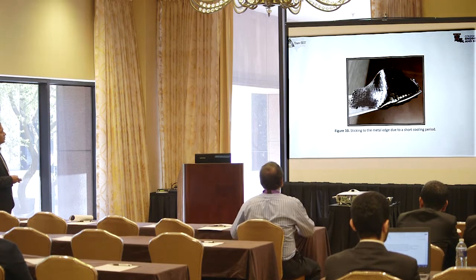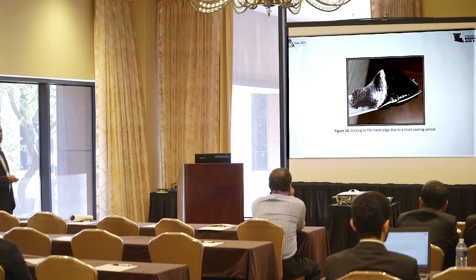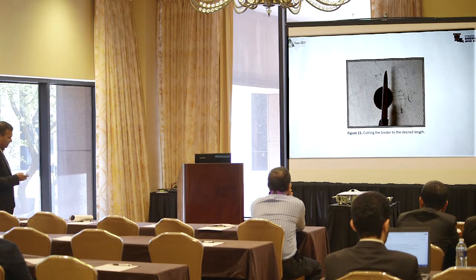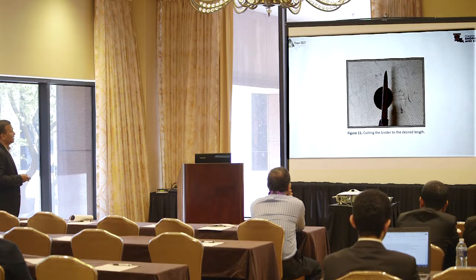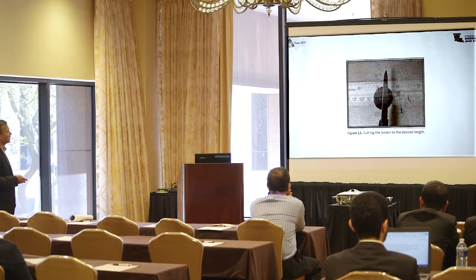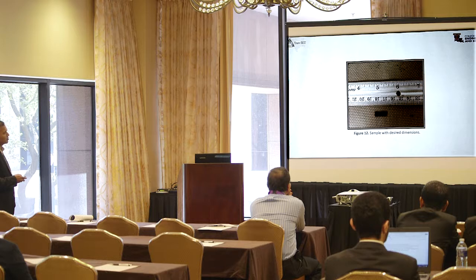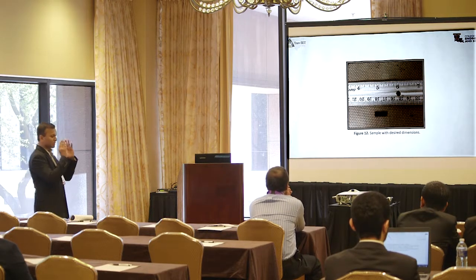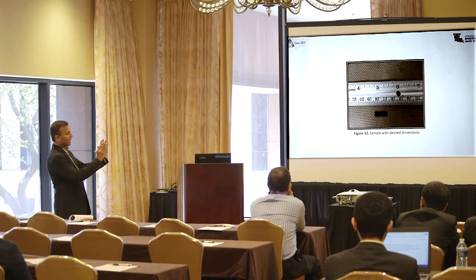And then if you do a short cooling period, because as you need to cut, you can see how it looks, and you understand, as you all have some familiarity with these materials. As you can see, it's not standing, it's actually lying on the mat, the sample, and you cut the binder to the desired length, so you can cut it. Length is not that important because when you put the sample in, you will see that it adjusts to the perfect length.